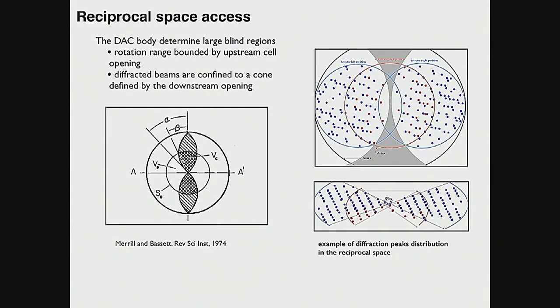Still, you have a problem of access to the reciprocal space. It's going to be limited, obscured by your diamond anvil cell, and by the technique you're using. In most cases, single crystal, you do a simple rotation along a vertical axis. So this is a plot of real data. This is far from the ideal hemisphere of peaks that you would want to have. That's good enough for high symmetry structures, but it might not be good enough for every structure.